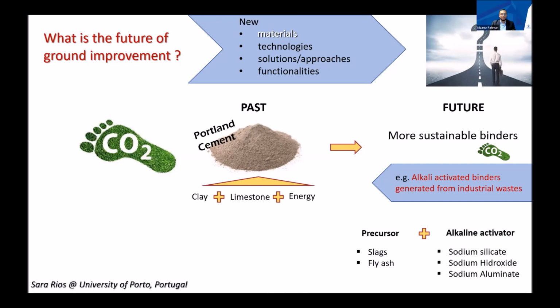Sara, I have a question for you. What would be the percentage of fly ash for your project? Yes, I'm studying up to 30%, for example. I think that's a reasonable amount, but we can use more or less depending on the conditions. Yes, 20 or 30% of the soil, for example. A ratio of fly ash to soil of 0.2, 0.3.